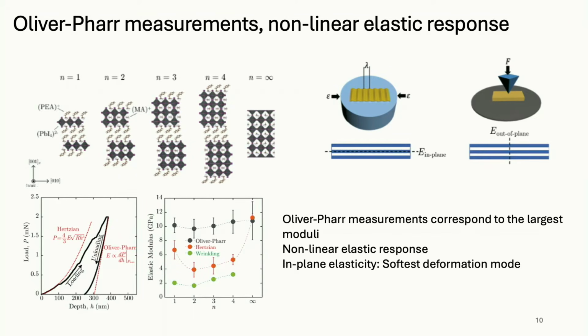I'll say more about this as we go, but basically you can see here that the material is quadratic for a while, and then there are these jagged regions. These are referred to as pop-ins. We think there are various defects that are created. We can call this a single crystal if we like, but it's such a soft material. There are lots of sliding defects and voids. And so as you compress, you're actually improving the crystallinity as you go. And so we think that the unloading part of the mechanical testing curve is more representative of the intrinsic properties of the material.